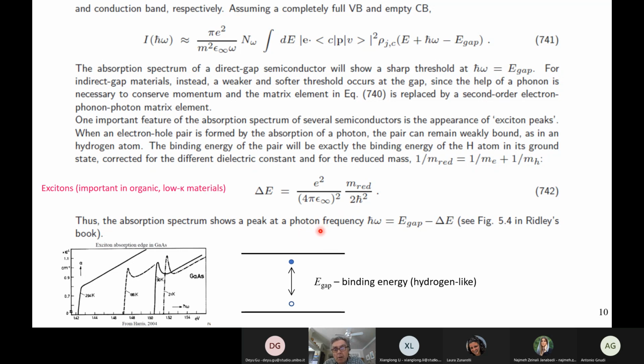And again, when you talk about band gap, it is very important to distinguish, as we saw discussing the band gap narrowing effect, between the electrical band gap, which is what you measure by exciting carriers above the gap thermally in a non-radiative fashion, or electrically by injecting carriers over some built-in potential, and the optical band gap, which is what you have by optical transitions.